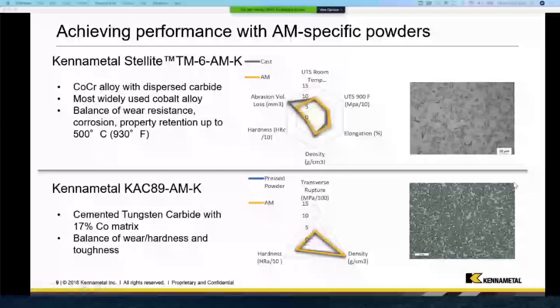And in addition, on the tungsten carbide side, we are prototyping with products that have a lower matrix content, so cobalt matrix down to 12% and 10%. And we are also introducing a carbide that has a matrix that's a combination of cobalt and nickel that will be a more corrosion resistant version of the tungsten carbide grade.